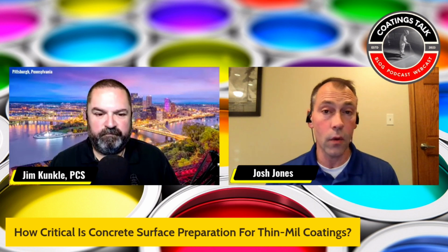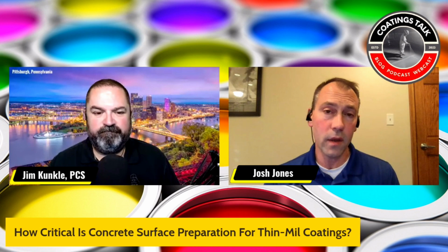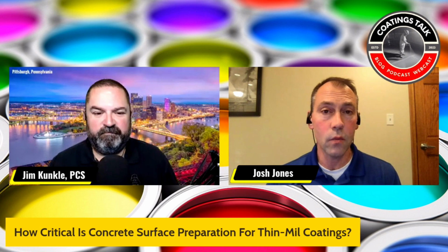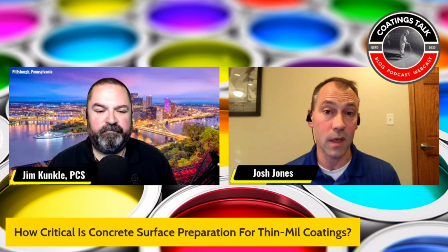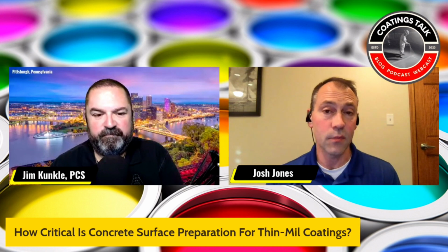So when that liquid, just like oil as an example, when that coating flows into the concrete and then within a certain amount of time starts to gel and harden through reaction, it turns into a hardened layer. In most cases, we'll just say plastic, that is now fused to the surface of the concrete. So what that means is if I do it right, that coating will not come free from the surface of that slab unless the slab itself and its tensile strength is exceeded, and literally that surface delaminates, meaning the coating doesn't peel. The concrete actually breaks in order to release it. That's a properly adhered coating system.